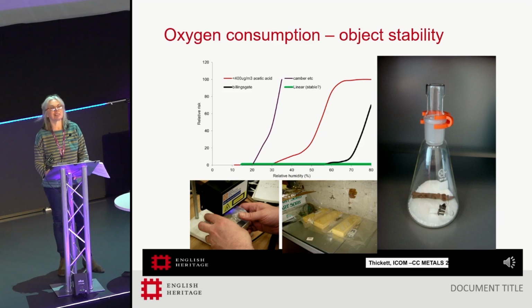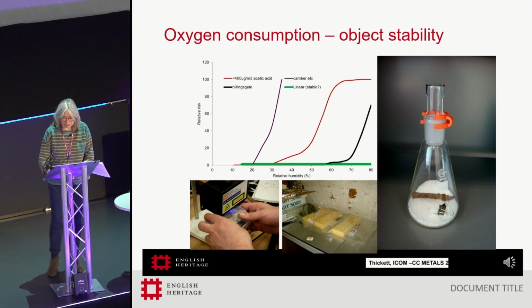This is how we test oxygen consumption. The photo on the right is of a conical flask with an iron object being tested inside with Art-Sorb silica gel to maintain a 50% relative humidity level during the test. The middle lower photo shows the same process with an array of larger objects encapsulated in heat-sealed Escal bags with Art-Sorb cassettes to control the RH. The photo on the left shows testing of the oxygen level. The graph is from Dave's research.